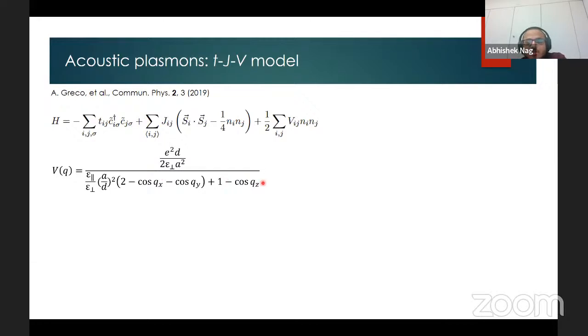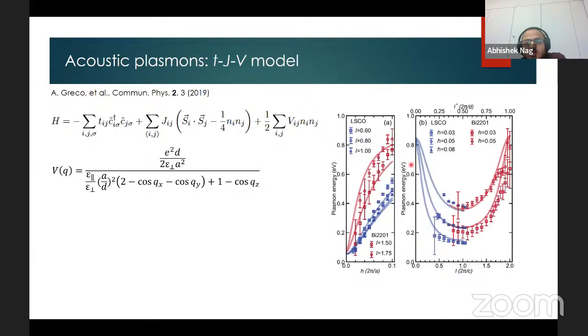Three-dimensional form of long-range Coulomb interaction to calculate the dynamic charge susceptibilities. And if we plot the extracted plasmon energies from experiment and then compare the dispersions that we obtained from these model calculations, we see a very nice match for both the materials, further confirming that we are indeed observing acoustic plasmons. And as you can see here, the plasmon energies do not exactly go to 0, but there is a finite gap present. And this is due to the interlayer hopping interaction that is included in the theoretical model. And this gap should be much enhanced in the infinite-layer cuprates where the interlayer spacing is much smaller.